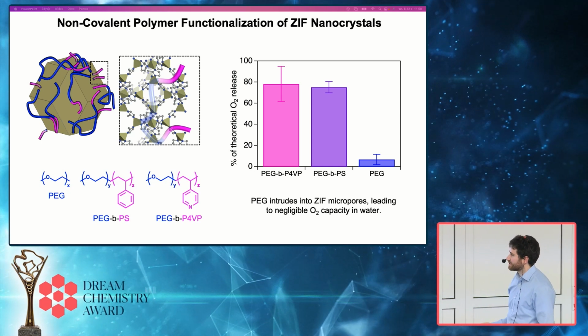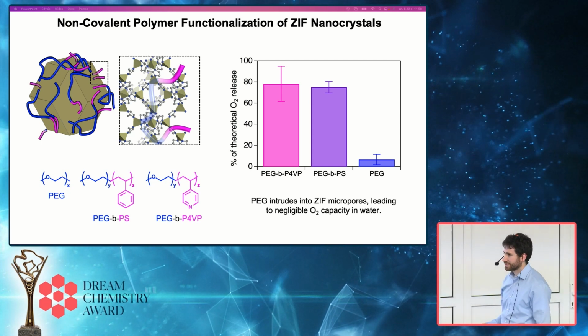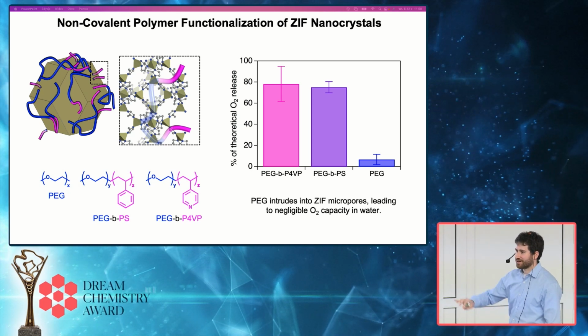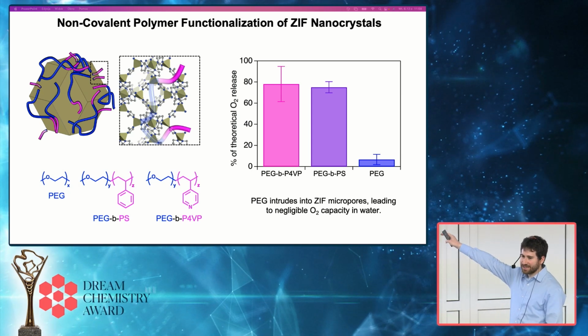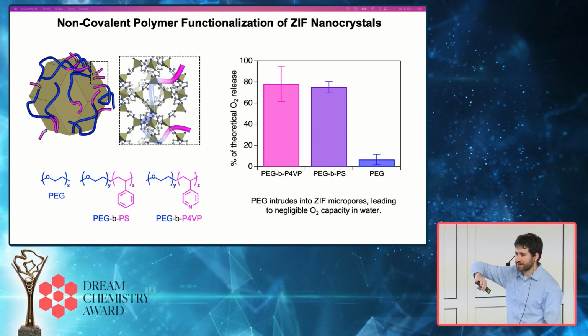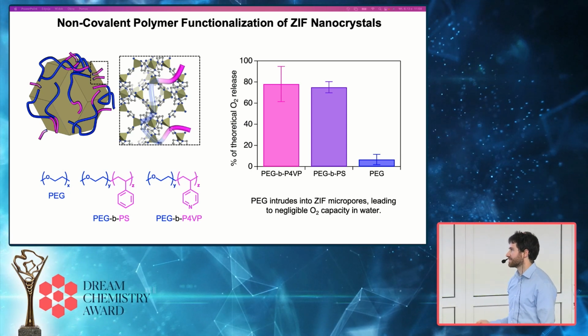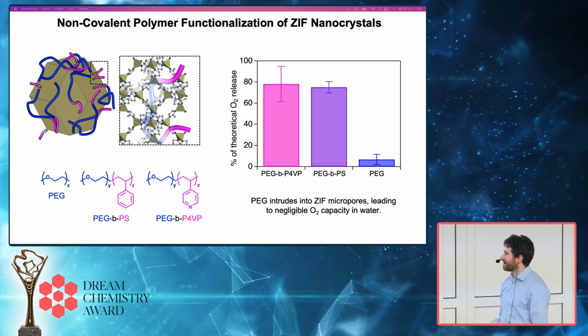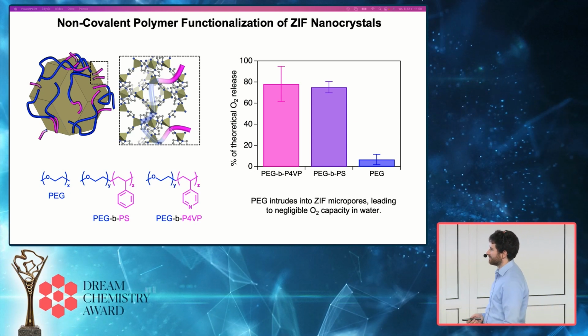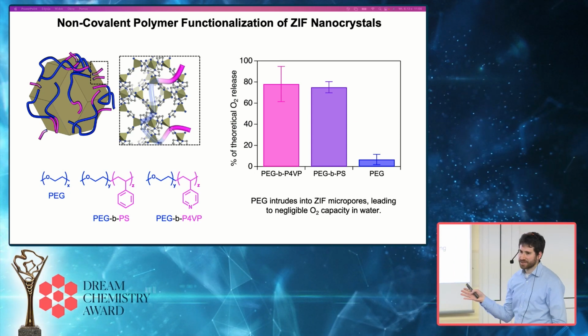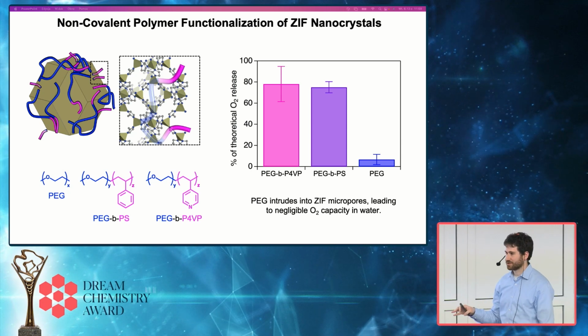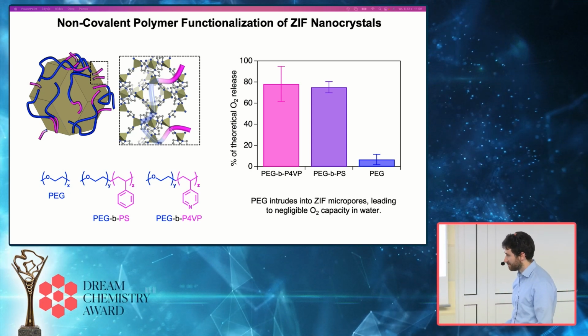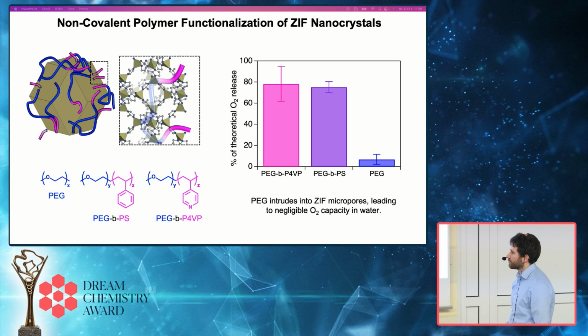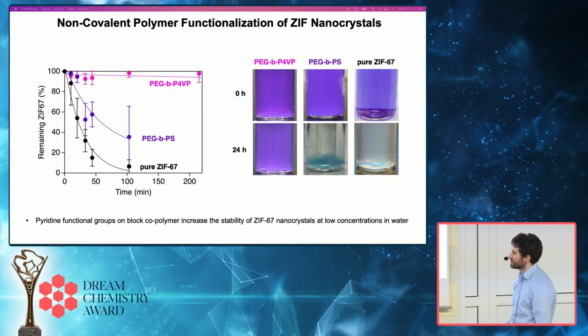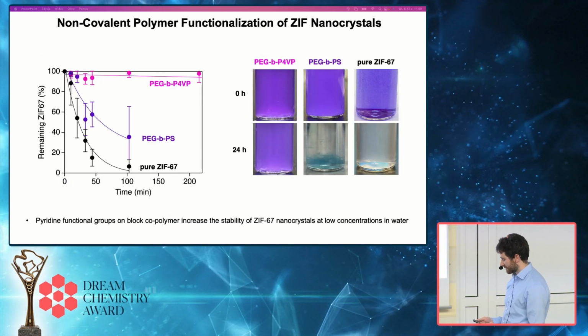So basically, we think that these kind of blocks are serving as anchors that are holding some of the polymer on the outside and preventing PEG from getting inside the particles. But again, this is something that we're still really working to understand, and in particular thinking about the thermodynamics of these interactions of polymers with the surfaces and internal pores of these materials and how we can manipulate that. We do see really interesting differences in the stability of these particles as well.